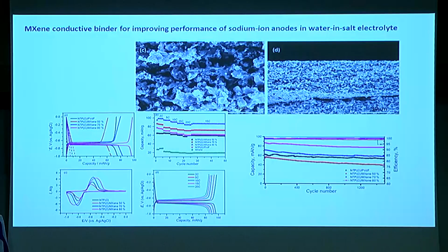And you can see here the black line is the NTP with the PVDF, and the pink line is the NTP with the MXene. And you can see that we got a significant increase in the capacity due to the fact that MXene is a binder, but also has some capacitive-type response. And with this we can get very nice cyclability. In fact, I think we got more than 2,500 cycles, but here we present only part of the cycles.